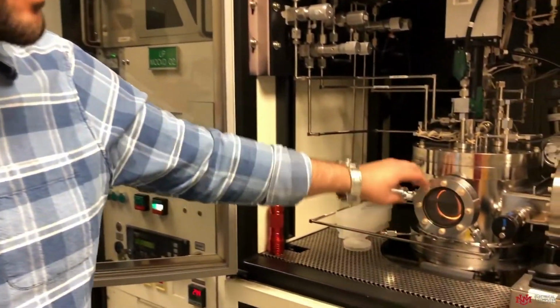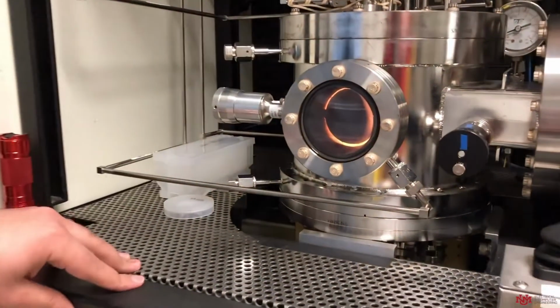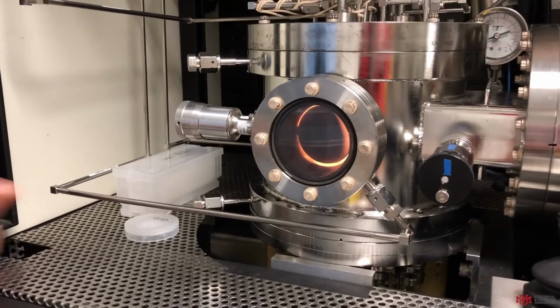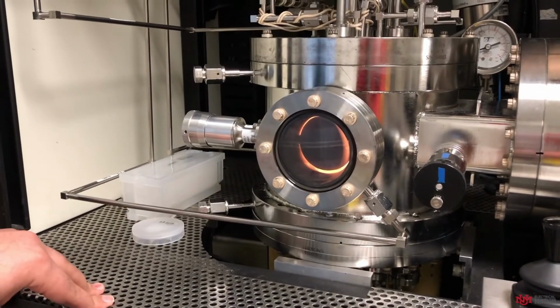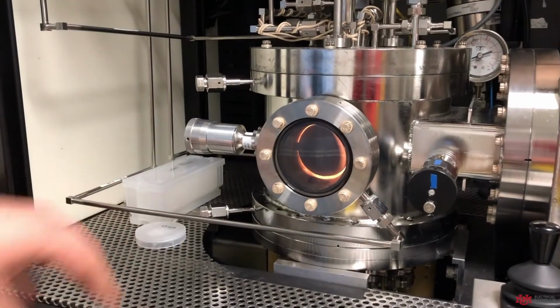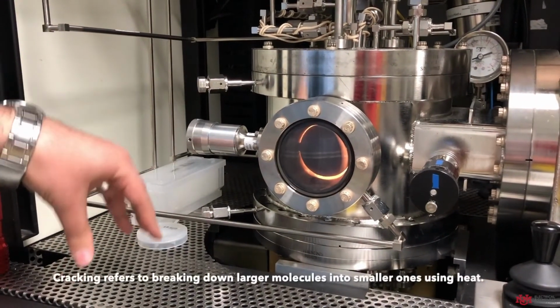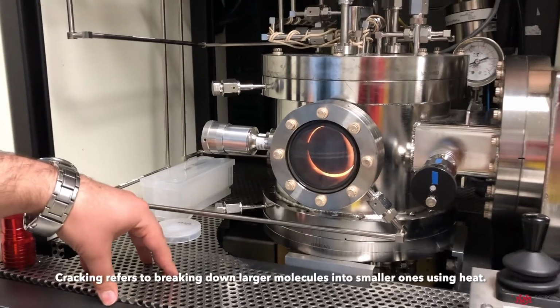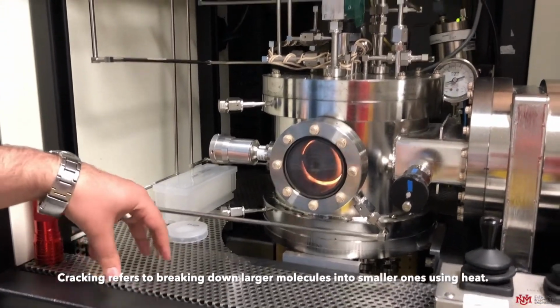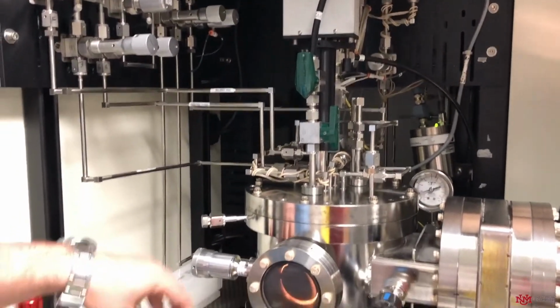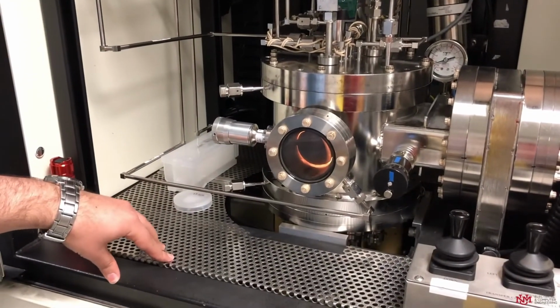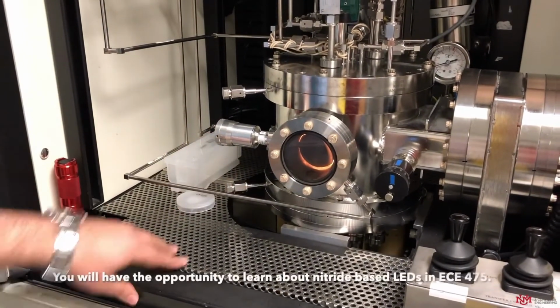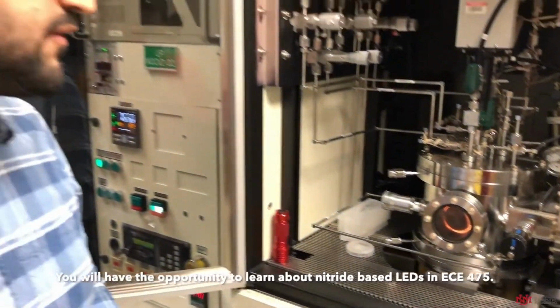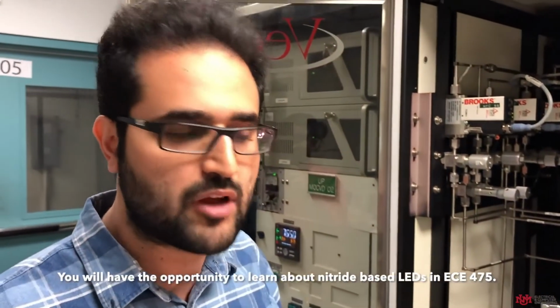As you can see here, it's actually lighting up. It's because the susceptor is being heated and it's rotating at 1500 RPM, and when the gases go there, they start to crack. Let's say nitrogen from the ammonia cracks and gallium from a metal organic source cracks, and then they react on top of the surface and form the gallium nitride. And depending on what sources you introduce, they can form different alloys from indium gallium nitride to aluminum gallium nitride, and even quaternary alloys like indium aluminum gallium nitrides.